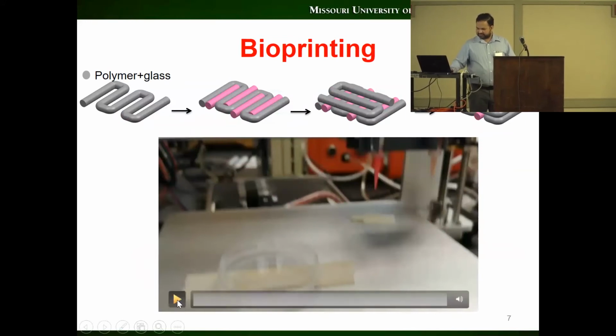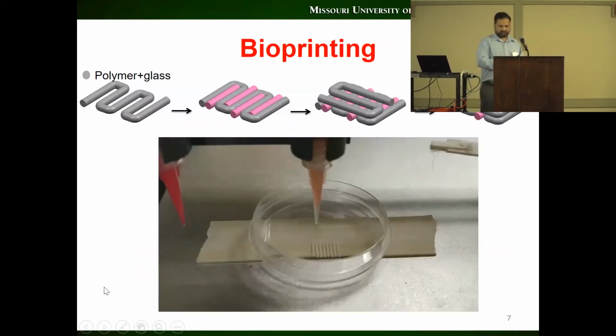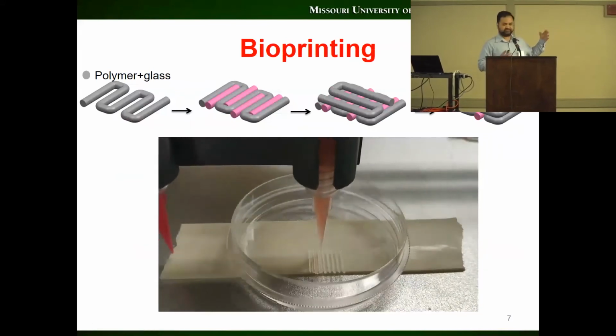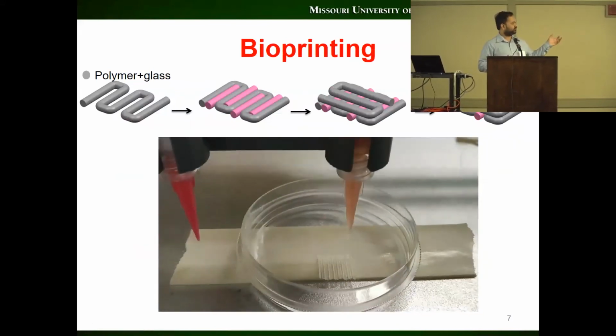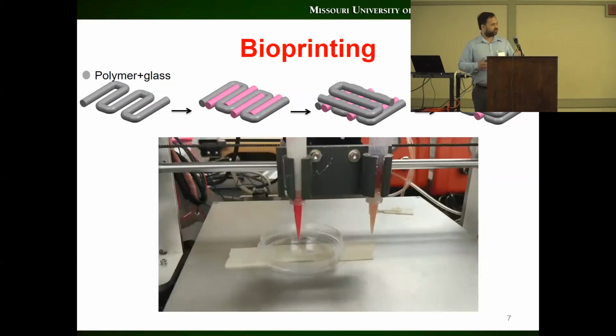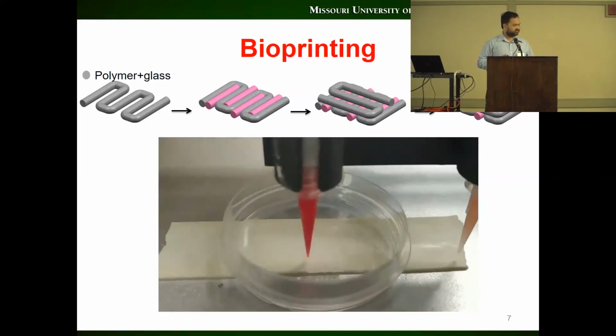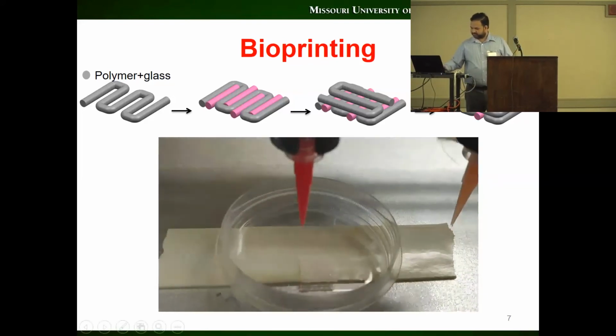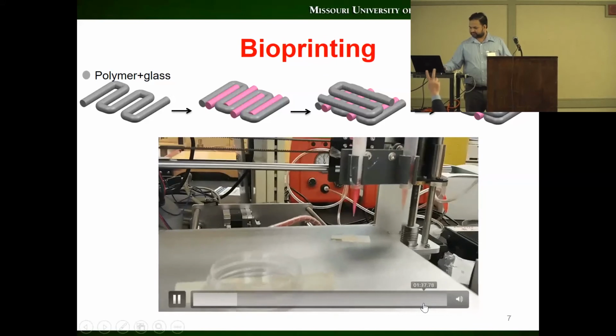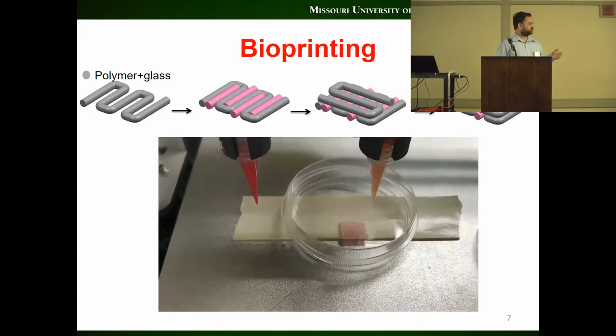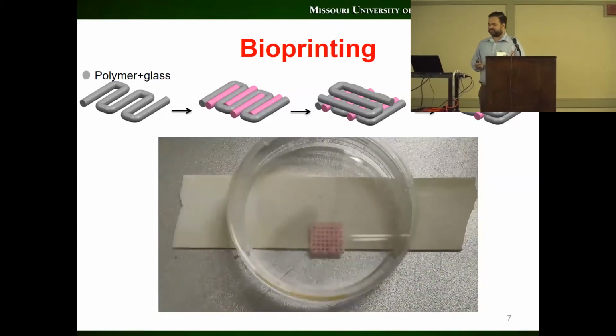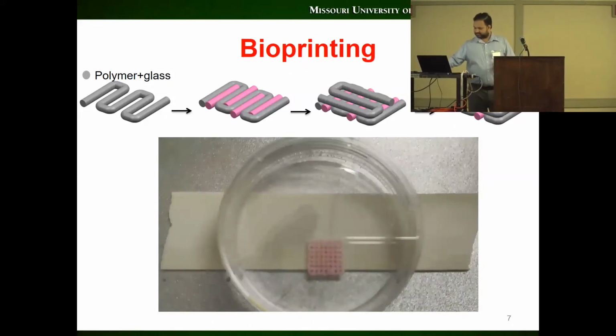So this is a short video of the bioprinting. We have two different syringes. In one syringe, we use bioactive glass and polymer matrix. In the second syringe, there is bioink. It's alginate gelatin-based. We mix stem cells in that. So it is a deposition process in a layer by layer fashion. And towards the end, you can see it starts to form. We can do it in different shapes. This is just a testing phase, so you can see a simple square shape.